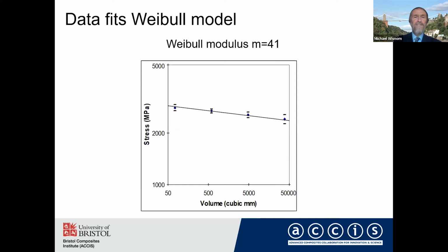And if you plot that as a Weibull distribution with a log-log plot, then the Weibull model seems to fit the data quite well. And the Weibull modulus for that is about 41, which is a relatively high value, which reflects the fact that although there is variability, it's not that huge.